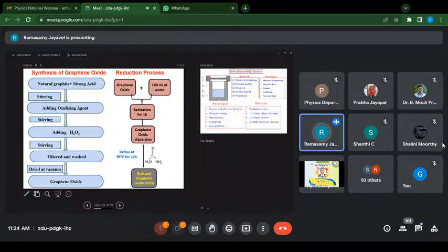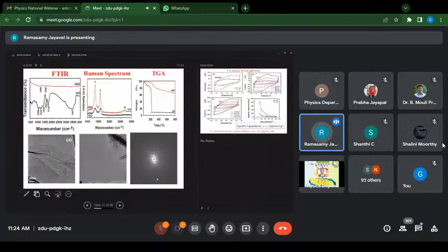And then from the graphene oxide, in order to reduce it to graphene, we can use some kind of reducing agent. Here we have used thiourea as the reducing agent. So when you mix with this reducing agent and reflux it at 95 degrees Celsius for 12 hours, you get what is called reduced graphene oxide. And if you are able to reduce all the oxygen functional groups, then it becomes graphene. But in the chemical reduction process, there will always be residual oxygen functional groups present in the matrix. Therefore, we safely call it reduced graphene oxide.